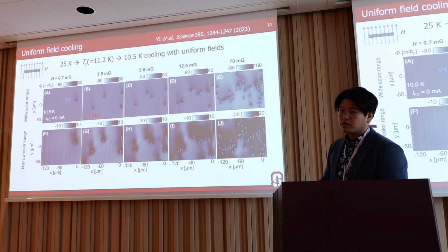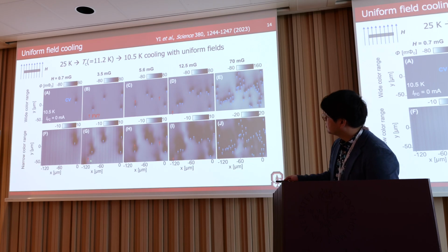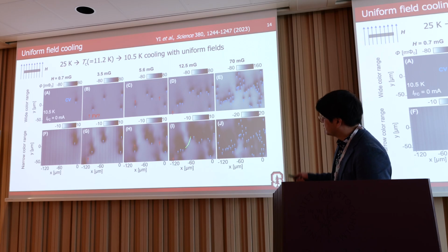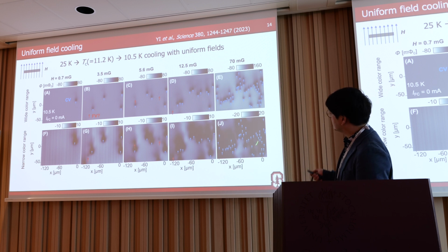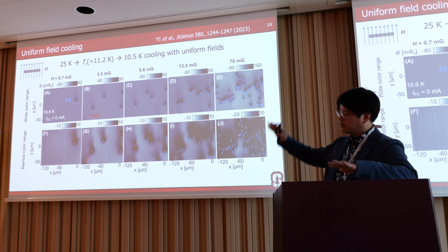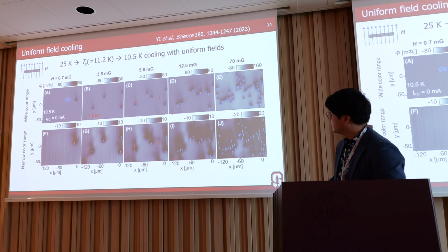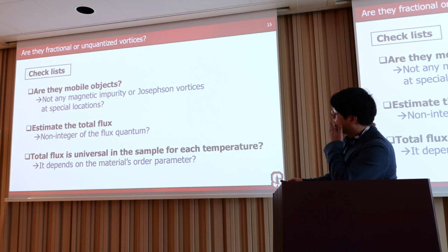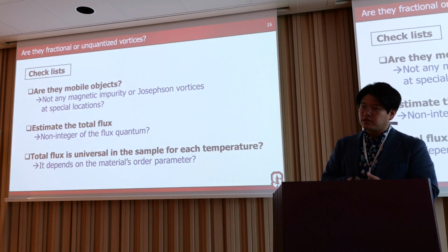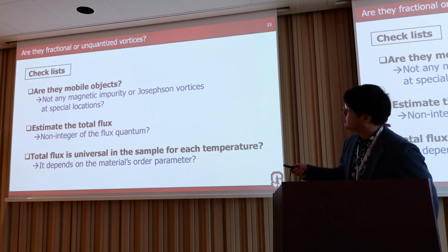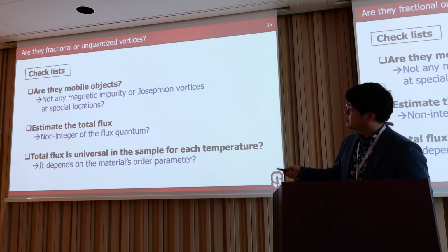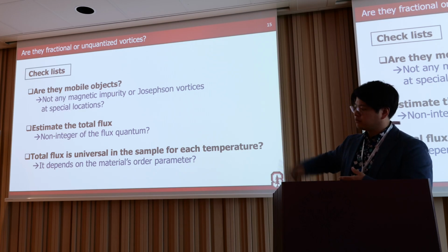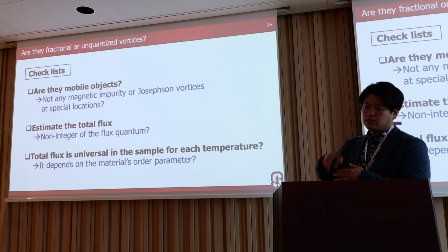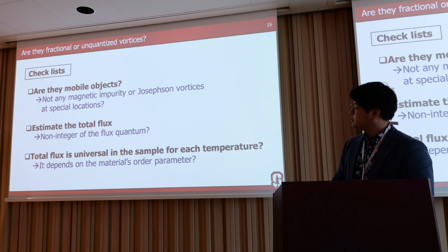So I repeated the measurement, with field cooling, and in different thermal cycles we see different fractional-vortex-like objects. At a higher field, the other integer vortex magnetic fields overlap each other, and we could see them. So let's check whether this is a fractional vortex or something else. I made three checklists: whether it's a mobile object, whether the flux is totally quantized or fractional, and whether it is universal within this sample, including the temperature dependence.